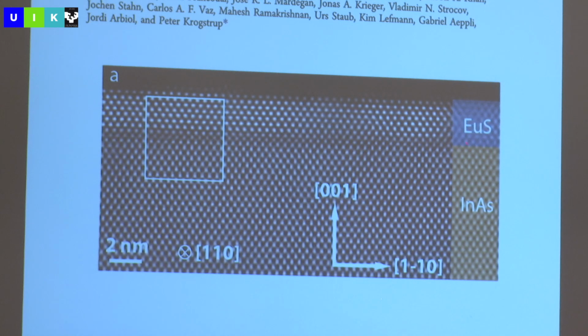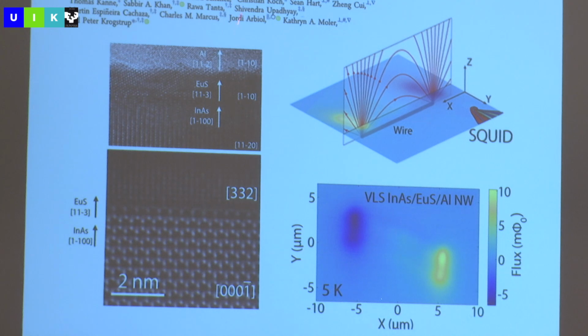So there's the europium sulfide, there's the indium arsenide, there's the crystal interface, and here's Peter Krogstrup, now a professor at University of Copenhagen, growing these interfaces. We're not quite there yet. We have to take one more step and put the 3 materials together: semiconductor, ferromagnetic insulator, and superconductor. Here is indium arsenide, europium sulfide, and aluminum. And you can see it's not the greatest interface.